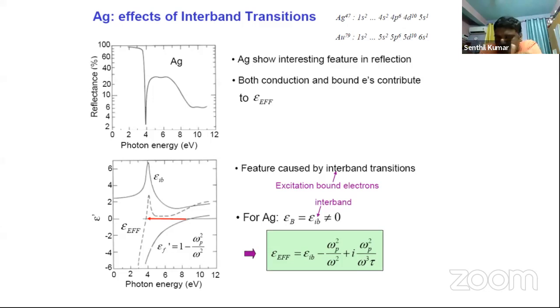So it depends on the electronic configuration of the given system, and that's where the bound electron contribution becomes very important. That's why we cannot neglect it. Here the bound electron contribution, because of this hybridization, is called interband transition: a transition from 5d to 6s in the case of gold, and 4d to 5s in the case of silver. That's where the experimental data and the theoretical data do not match.